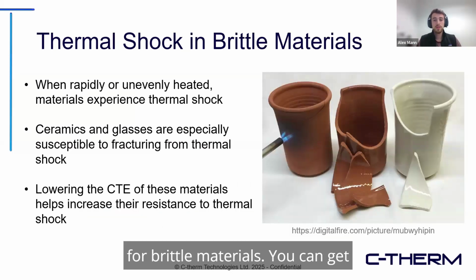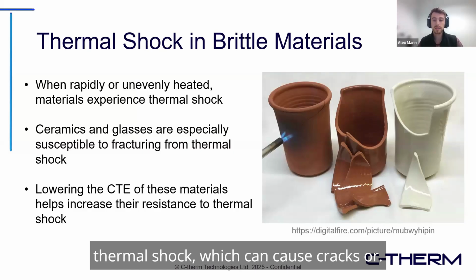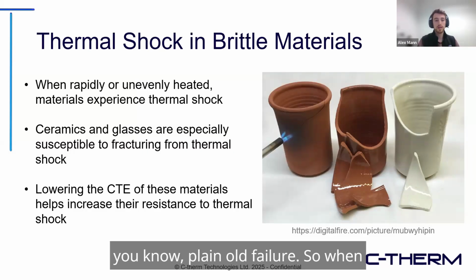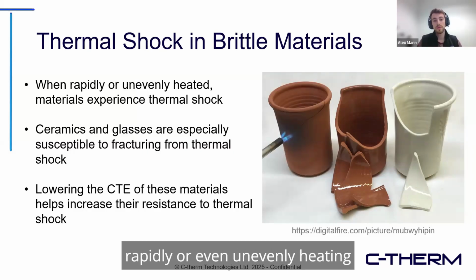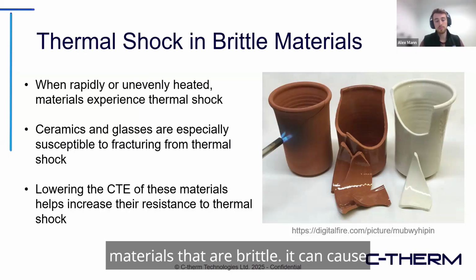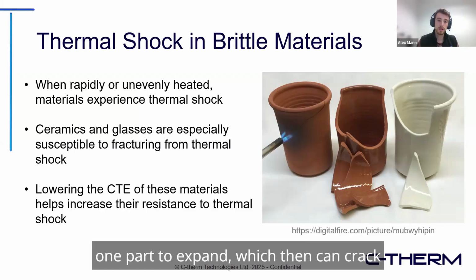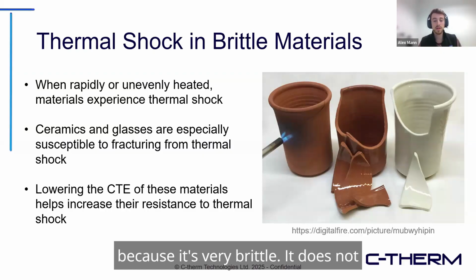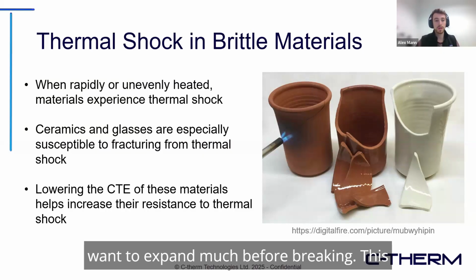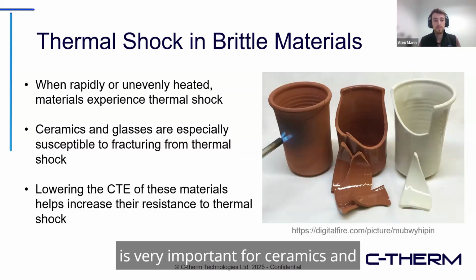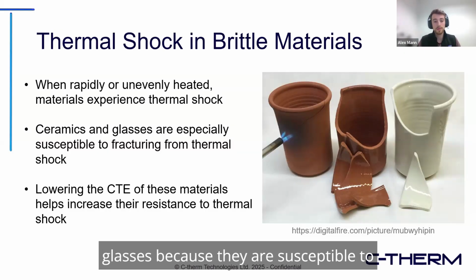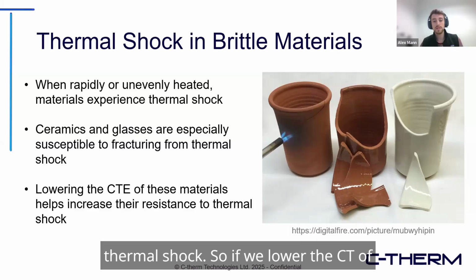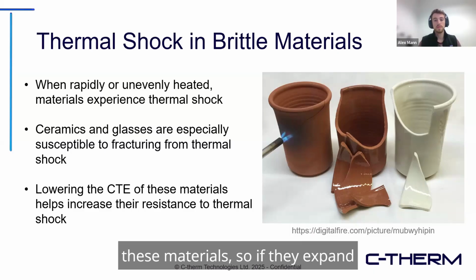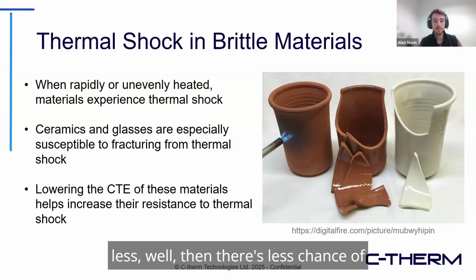For brittle materials, you can get thermal shock, which can cause cracks or plain old failure. So when rapidly or even unevenly heating materials that are brittle, it can cause one part to expand, which then can crack because it's very brittle. It does not want to expand much before breaking. This is very important for ceramics and glasses because they are susceptible to thermal shock. So if we lower the CTE of these materials, so if they expand less, well, then there's less chance of them breaking or cracking or failing.